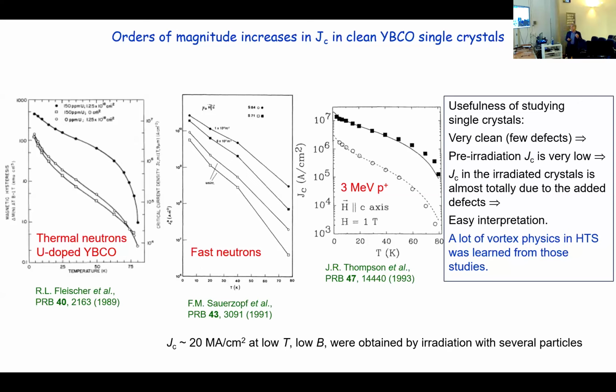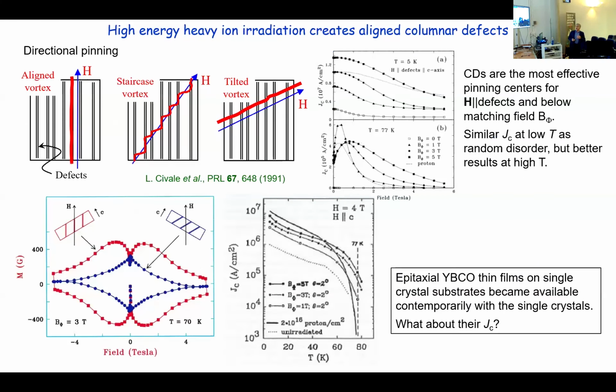And in fact, a lot of vortex physics in these new materials was learned from this type of single crystal irradiations. And people were able to reach critical currents, including me, in the range of 20 megaamps per square centimeter at low temperature, low fields. By different methods give similar results.